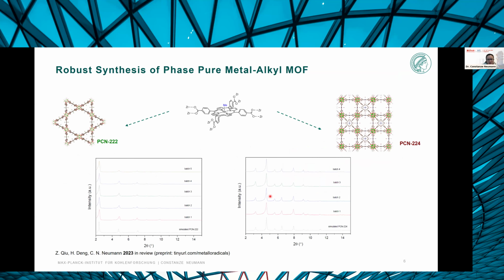So we were very happy that after a significant amount of optimization, we found robust syntheses that would allow us to access these rhodium methyl intermediates in 2 different zirconium MOFs, PCN222 and PCN224, so that we would have the ability to look at 2 systems that are made of the same building blocks, but where the rhodium sites are spaced in different manners, which is something that is, I would say, relatively unique to MOFs, that you can actually investigate what the effect of the distance between the rhodium centers would be on catalysis to exclude, for example, any reactivity that relies on the proximity of 2 rhodium centers.